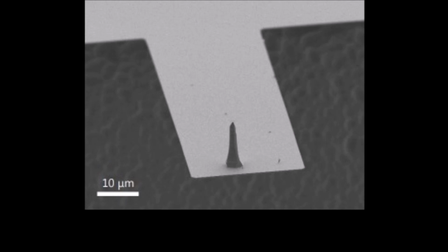This is an SEM image of a high aspect ratio tip and cantilever fabricated using the method just explained. This method produces an ultra thin and sharp tip that helps in increasing the resolution of the image taken. The three faces of the tip also help in scanning deep valleys on the nanoscale topography of the surface. And silicon nitride is used because of its strong material properties to avoid wear on the AFM tip.